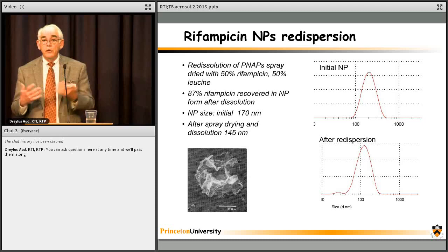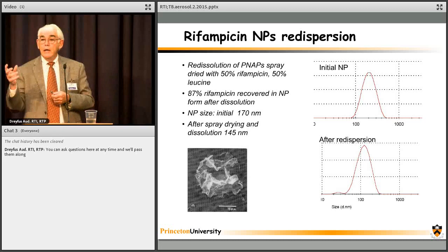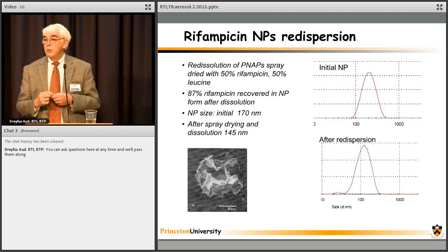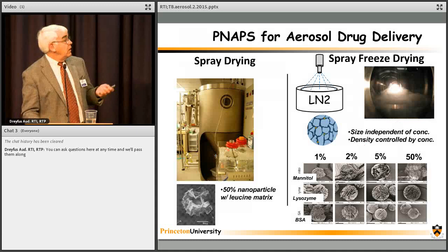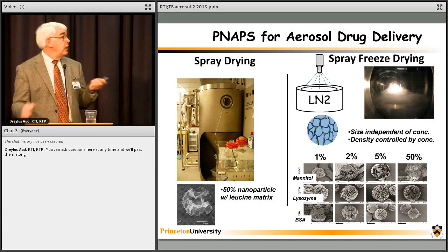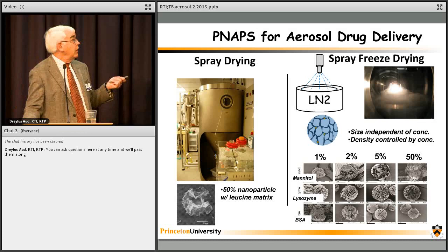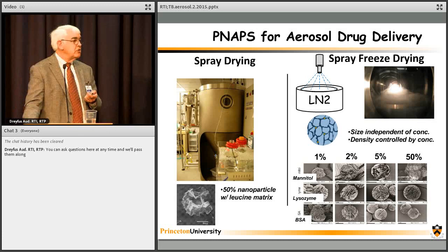So here we have a way of getting an aerosol formulation to get deep lung delivery, but then being able to present these smaller particles which will stay resident in the lung for longer periods of time. That's one technique, using Dave's technique of this really careful drying to make these crenellated particles. As I said, we worked with Amgen, and they had commercialized a process called spray freeze drying. Actually, they built the plant, they put the line together, and then they killed the project at the very end. But they had demonstrated they could scale this spray freeze drying process up.